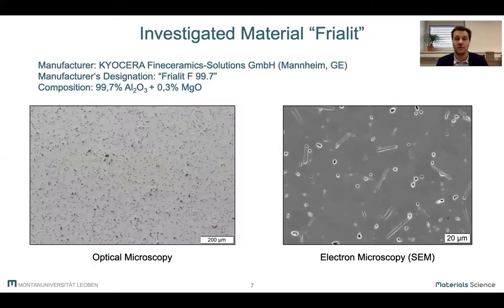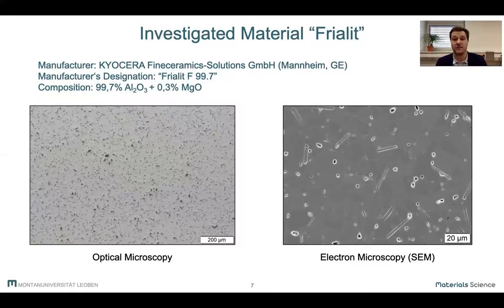The material we tested was called Frialit, which is alumina with a small amount of magnesium oxide. It was sourced from Kyocera in Germany, and we received two rods of different diameter, which were cut into discs at our own facility. Since we found a significant difference in microstructure and mechanical properties between those two rods, we treated them as separate materials.